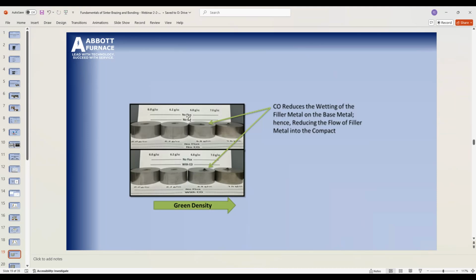Okay, up above here we have no CO, and you notice how it infiltrated, and then only at a 7.0 do we see that we didn't get a lot of infiltration. As soon as we put that CO in the atmosphere, look at how you can already see remnants of the pellet, and at our 6.8 we were able to stop it from infiltrating. Okay, so now we don't have to be molding to a 7.0 to successfully sinter braze. Now we can mold to lower densities and still successfully hold that filler metal at that joint.